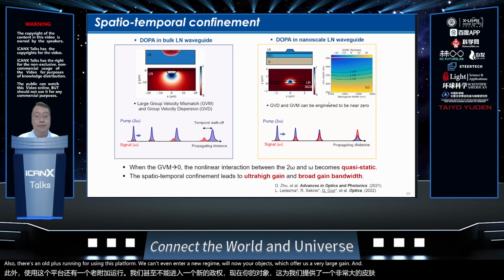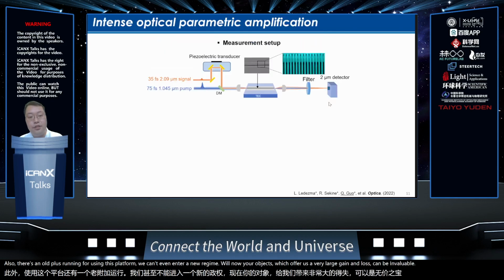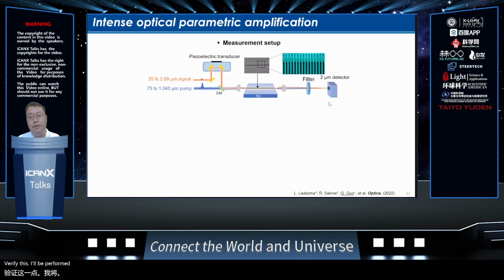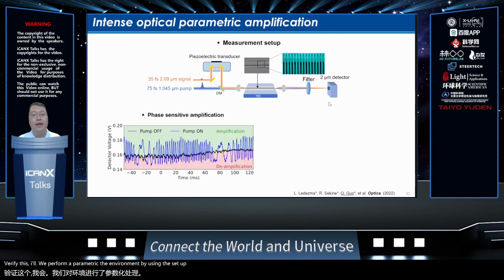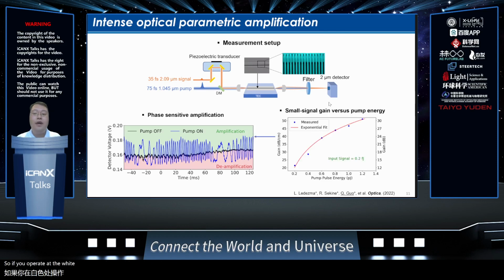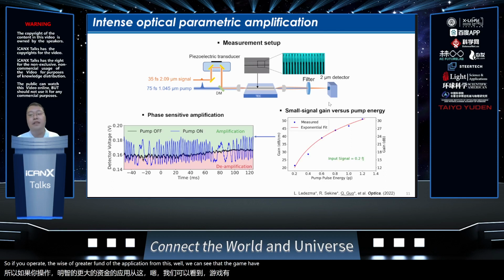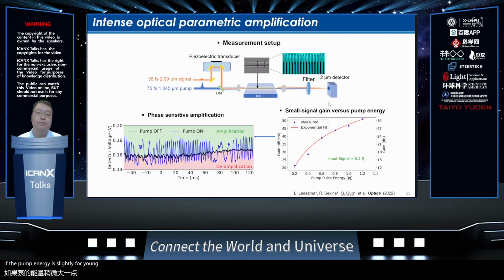and large gain bandwidth. To verify this, we perform a parametric gain measurement using this setup. And here are some measurement results. You can see at some point, we see the amplification of the signal at 2 micron. But when the phase is shifted by 180 degrees, we see the de-amplification. If we operate the device right at the point of amplification, from this plot, we can see that the gain can be even more than 50 dB per centimeter if the pump energy is slightly beyond 1 picojoule.